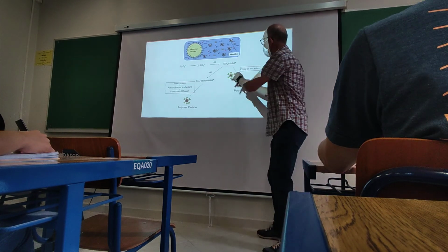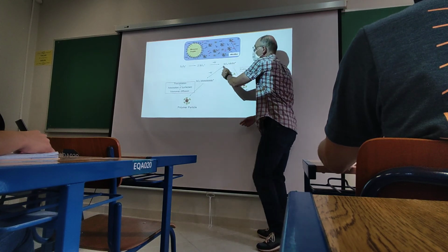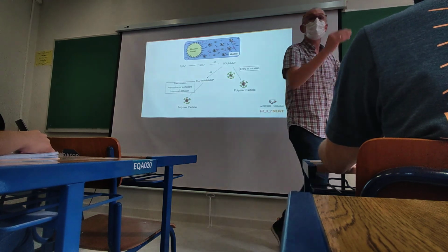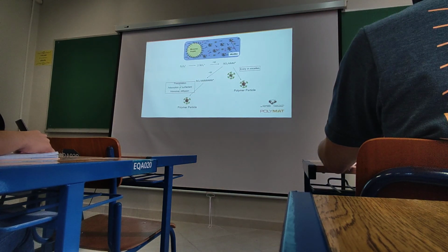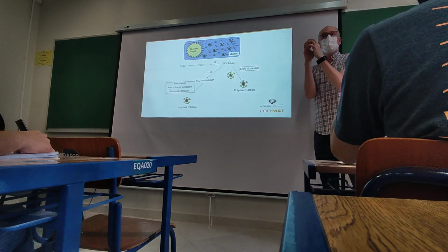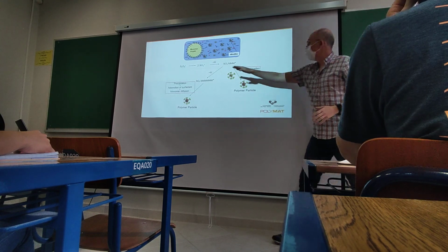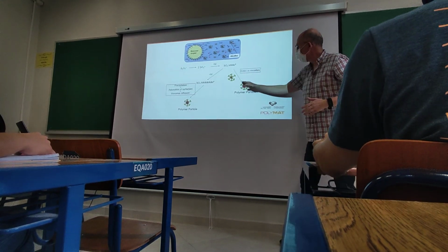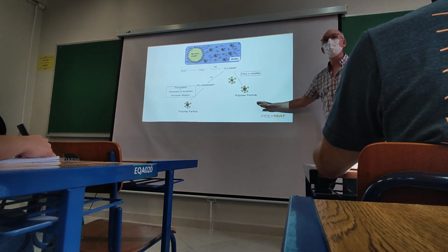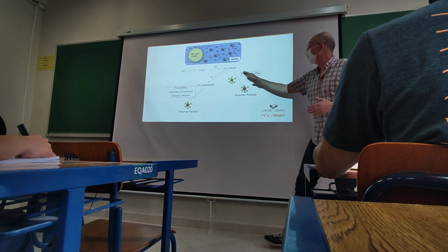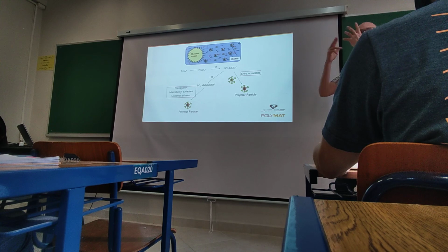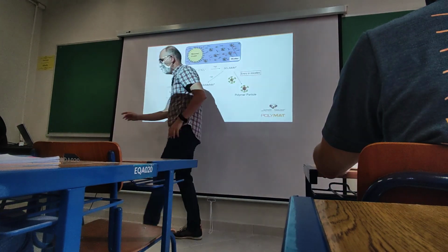In this case, this will not find micelles, therefore will continue growing, and it will continue growing until this becomes insoluble and precipitates. It precipitates, it will absorb surfactant, and then monomer will go to this and form a new part. So this mechanism, by formation of polymer particles by entry of radicals in the micelles, is called micellar nucleation or heterogeneous nucleation, and this way is called homogeneous nucleation. Okay? So these are two mechanisms that I will also cover tomorrow.